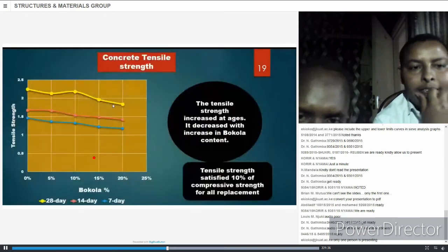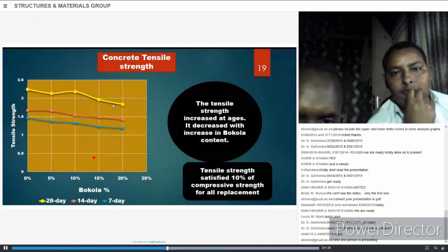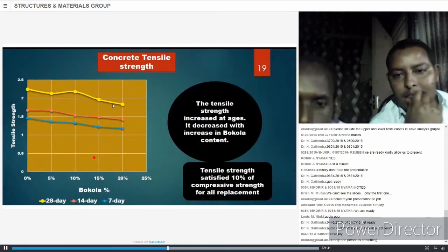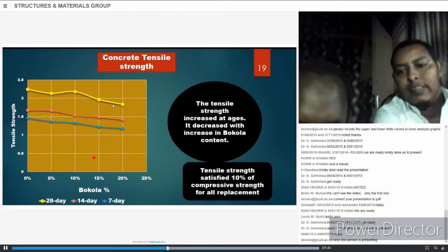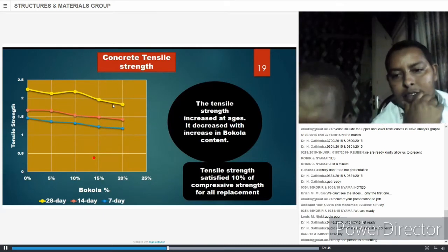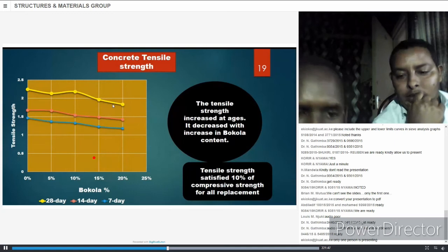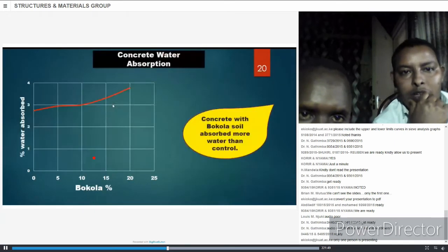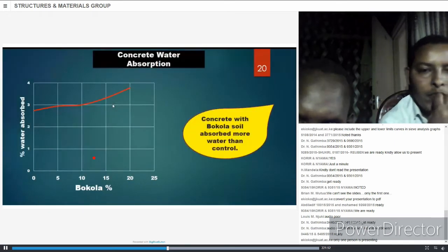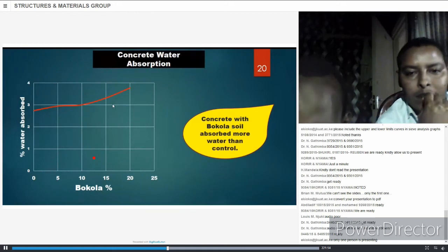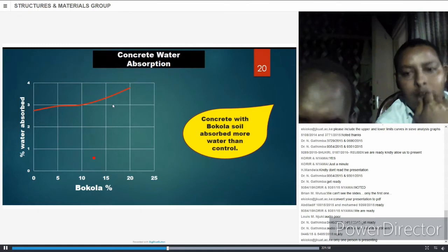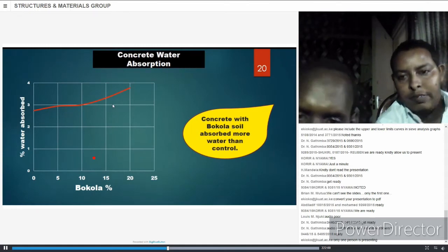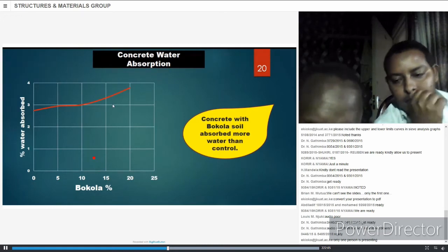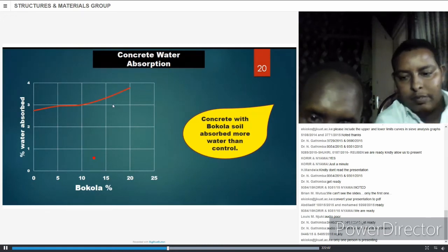The tensile strength also increased with time, that is 7, 14, and 28 days, but decreased with increase in bokola content. The tensile strength also satisfied the 10% of compressive strength for all the replacements. The concrete water absorption also increased with increase in bokola soil. This is due to the fineness of bokola, which is less fine than cement, hence creating porous spaces.